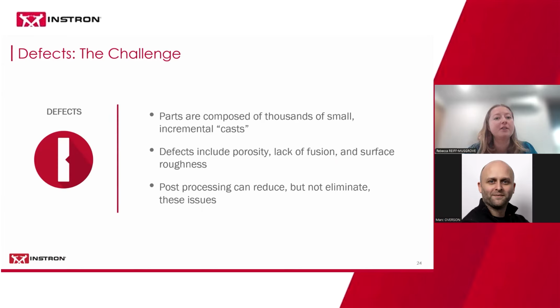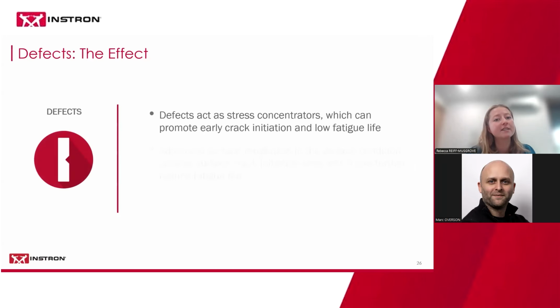And so we can get defects where these casts join, that include things like porosity, a lack of fusion between the casts, and also very high surface roughness from these individual melt pools. And post-processing can reduce these, so things like machining, heat treatment, but we don't always eliminate these issues. So what is the effect of these defects?